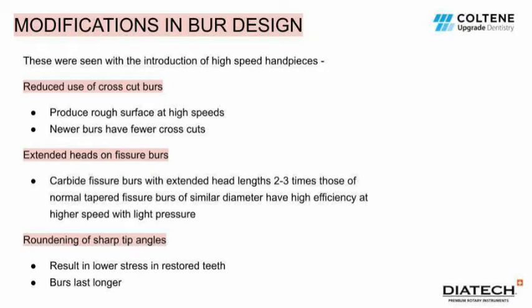Carbide fissure burrs with extended heads 2 to 3 times those of normal tapered fissure burrs of a similar diameter have high efficiency at a higher speed when light pressure is applied. And the next modification in burr design was the rounding of sharp tip angles of the burrs. This resulted in lower stress in restored teeth and longevity for the burrs.